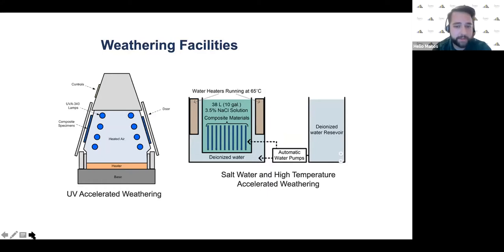In the past, we were able to achieve acceleration rates of 5 to 10 years for about a month of soaking. So two things happen when we soak the material in saline water. The first one is the material will absorb water, so it can swell up, and that in itself can cause some pre-stresses if we have some around the boundary conditions of the specimen. The second thing is the interaction between the material and the salt water can cause degradation in the mechanical properties. So we observe these two phenomena for the materials that we're interested in.